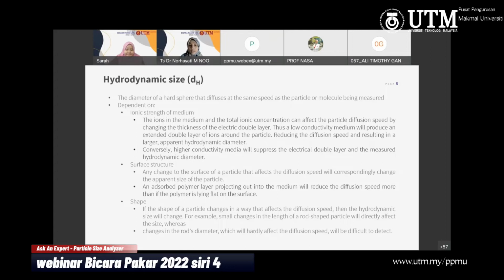The ions in a medium and the total ionic concentration can affect the particle diffusion speed by changing the thickness of the electric double layer. Some published papers suggest not to use deionized water for dilution, because they said it will give slightly different results in terms of size. A low conductivity medium will produce an extended double layer of ions around the particle, reducing the diffusion speed and resulting in a larger apparent hydrodynamic diameter. Sometimes if they use DI water, the result might be bigger when you compare with, for example, transmission electron microscope or scanning electron microscope. So you can see the sample size is slightly different because of this ionic strength.